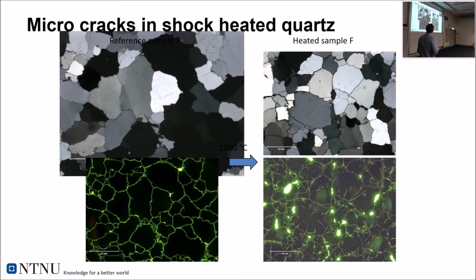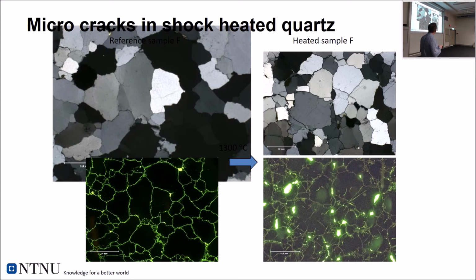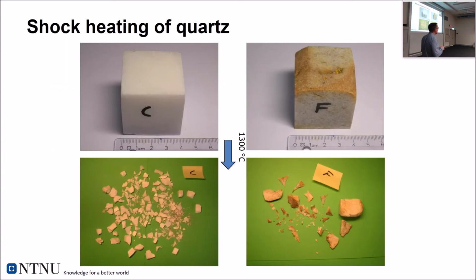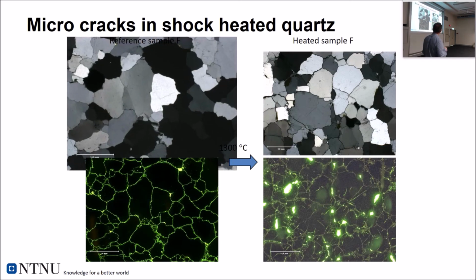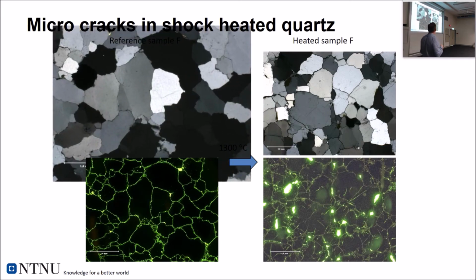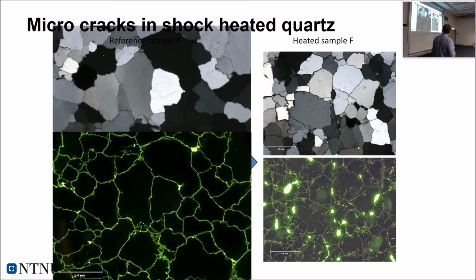So this one is the original rock. So we are talking about this material. This is how it looks before being heated. Nice, pure, fine quartz grains, nice, simple grain boundaries. And if you look into it in fluorescent light, you can see there is some space between grain boundaries. You see that epoxy resin has entered into the grain boundaries, but there is no internal damage in the grain. The grains are fine.